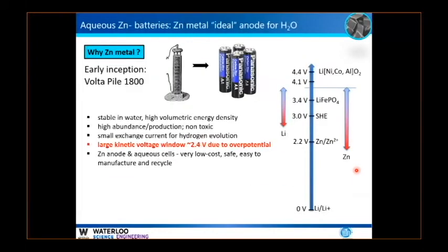And I'll just tell you about one of them that we've been developing, which is on zinc ion batteries. And the Volta pile developed in 1800 was based on a zinc battery. And it's still popular and very important today because zinc has all of these characteristics that I show you here. And in particular, the window that you can establish with zinc metal is actually fairly high due to the overpotential for what we call hydrogen evolution.